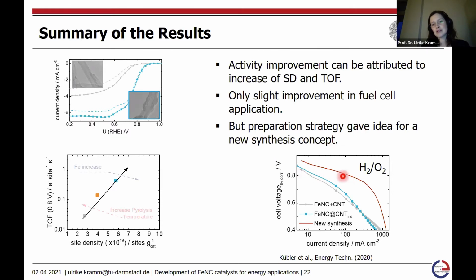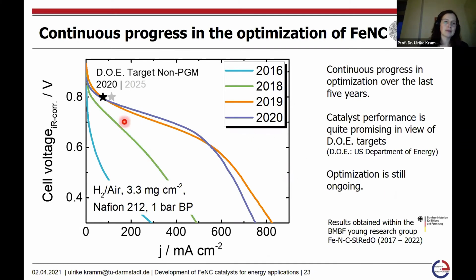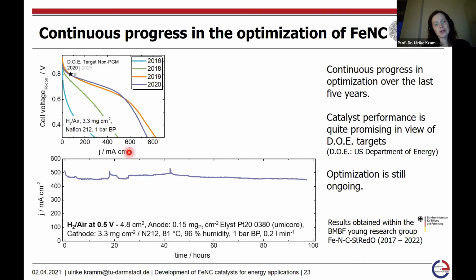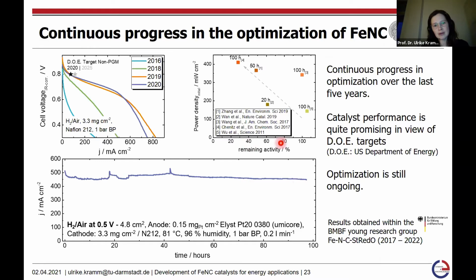And you can see that this new preparation strategy enables orders of magnitude higher activity within the fuel cell. So during the last years, based on that, we obtained significant improvements for the activity of our non-precious catalyst materials, and specifically also the stability. This is a potentiostatic test in hydrogen-air at 0.5 volts, and there you can see that we get quite good stability with respect to what you typically observe for FeNC catalyst materials. To get a better idea, I plotted here, from the leading publications in this range, the power density, as a measure of the activity, as a function of the remaining activity after 20 or 50 or 100 hours of such a potentiostatic test.